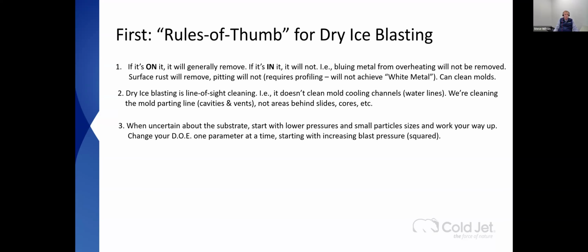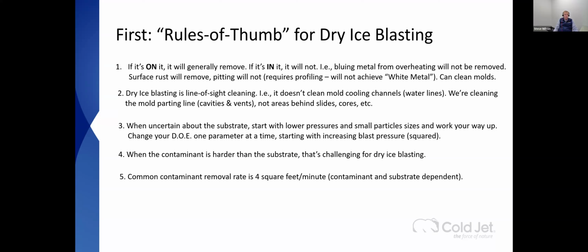When uncertain about a given substrate, its texture, its surface finish, its hardness, start with lower pressures, start with smaller particles, and then work your way up. Change your design and experiment one parameter at a time, usually increasing blast pressure, because we'll find out that is squared. When the contaminant is harder than the substrate, that's challenging for this process. You get dried hard glue on leather, for example. The pressures you need to get the glue off often leave a signature on a softer substrate. Common contaminant removal rate is about 4 square feet a minute.